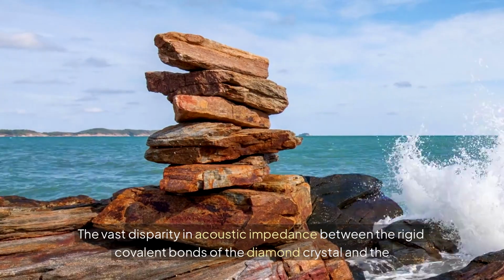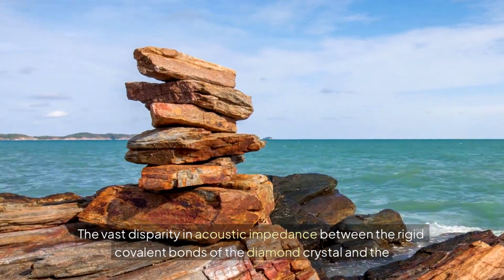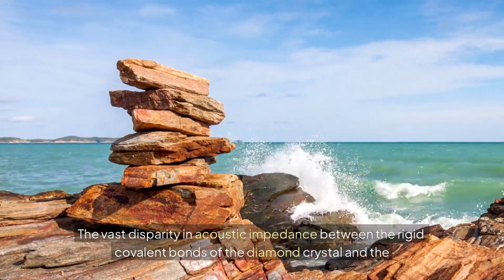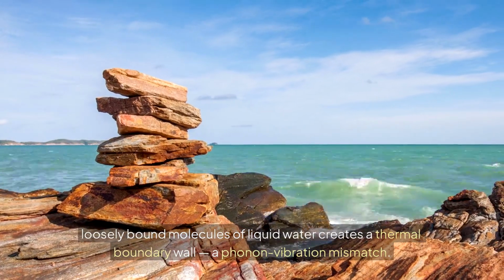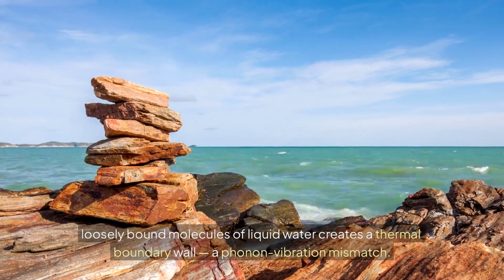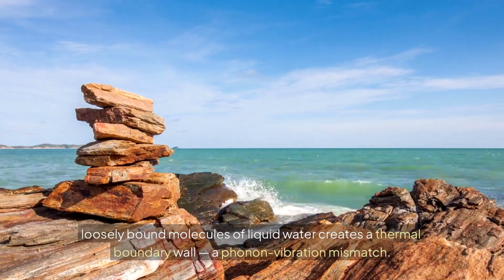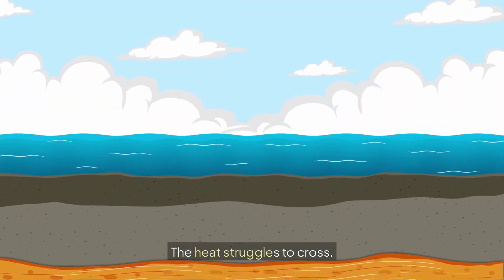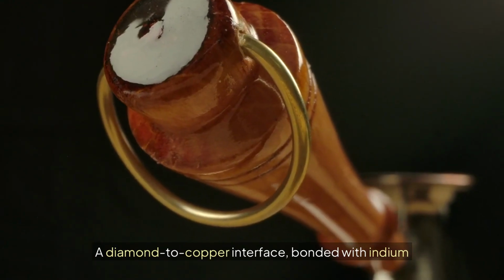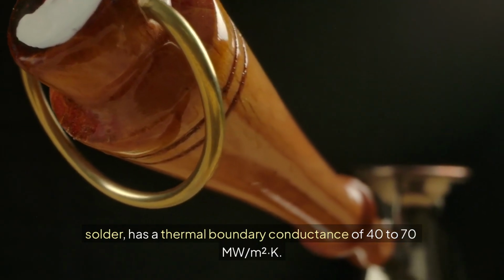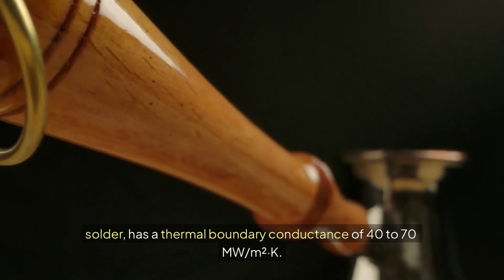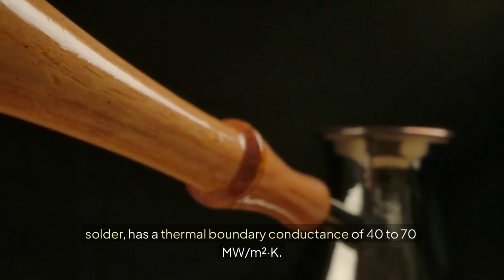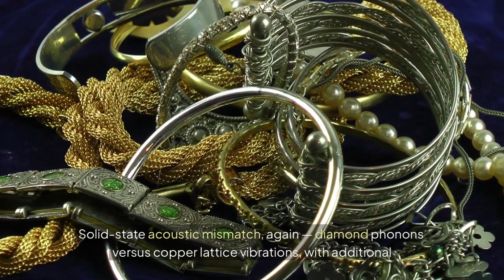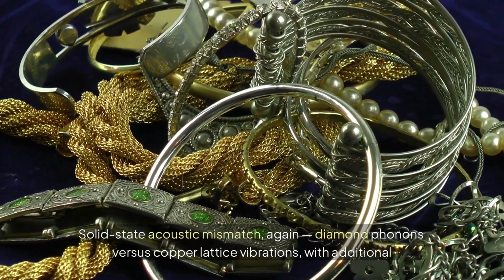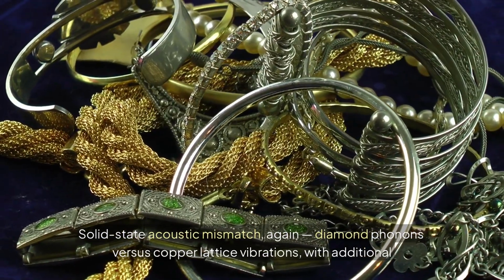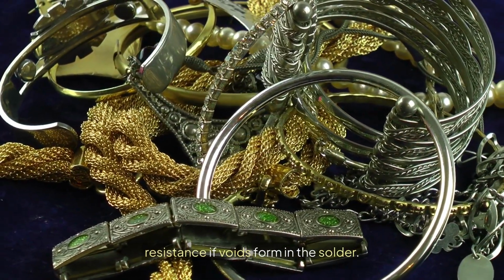The vast disparity in acoustic impedance between the rigid covalent bonds of the diamond crystal and the loosely bound molecules of liquid water creates a thermal boundary wall, a phonon vibration mismatch. The heat struggles to cross. A diamond to copper interface bonded with indium solder has a thermal boundary conductance of 40 to 70 MW/m²K. Solid-state acoustic mismatch. Again, diamond phonons versus copper lattice vibrations, with additional resistance if voids form in the solder.